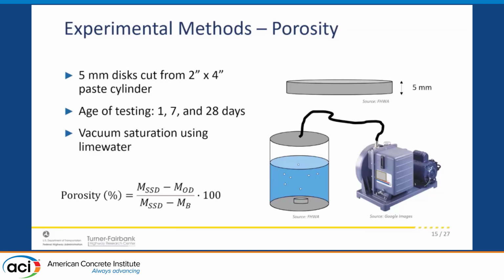Once you vacuum saturate them and you have the weight at oven dry and the weight at full saturation, you can back calculate the total porosity of your paste.